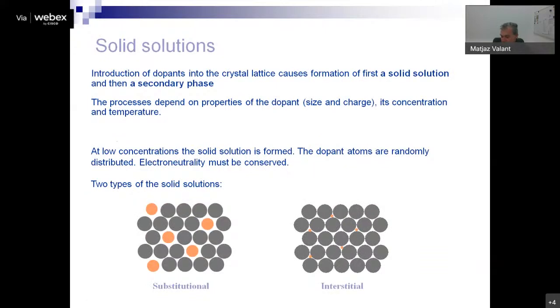There's another thing I would also like to introduce to you, and these are solid solutions. When we are talking about a small concentration of dopants or impurities within the crystal lattice, it's very likely that this small concentration will not change the symmetry of the crystal lattice. If this happens, we say we are within the solid solution range. The solid solution range exists in the concentration range of the dopant until the symmetry of the crystal lattice changes. When it changes, we produce a new phase, a secondary phase. And we call this critical concentration the solid solution limit.